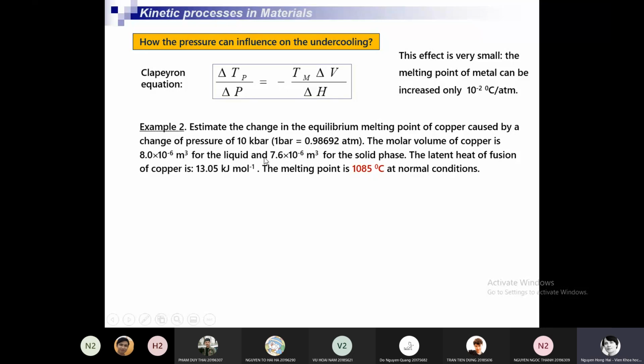See? So, for example, we have an example to estimate the change in equilibrium melting point of copper. Estimate this delta Tp caused by the change of pressure delta P of 10 kilobar. 1 bar is approximately equal to 1 atmosphere. If the pressure changes by 10 kilobar, how much do we change the melting point? We have to find the undercooling caused by pressure.